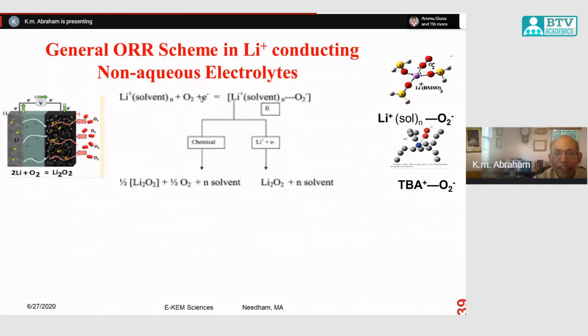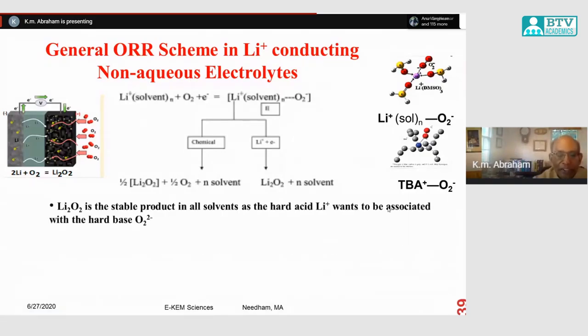The first step is a one electron reduction to form a superoxide that complexes with the lithium, so it has some stability, and the stability depends upon the solvent that you have. Then it either chemically decomposes to form peroxide or it is reduced further. You can reduce it further if it stays long enough in the electrode, which happens with certain electrolytes. The stable product in all solvents is the peroxide.